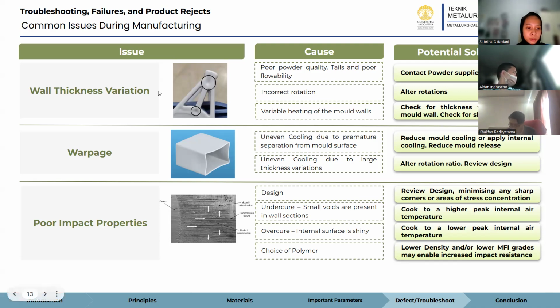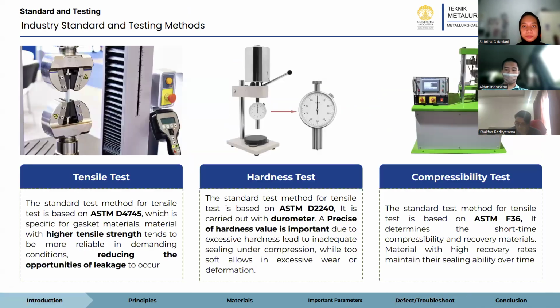And the last is poor impact properties. The cause is probably design, undercure where small voids are present in the wall section, overcure where the internal surface is shiny, and the choice of polymer. And the solution is first we can review the design, minimizing any sharp corners or areas of stress concentration, cook to a higher peak internal air temperature, or cook to a lower peak internal air temperature. And lower density and lower MFI grades may enable increased impact resistance.